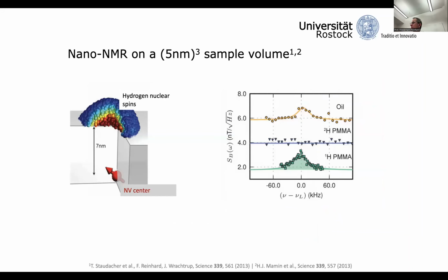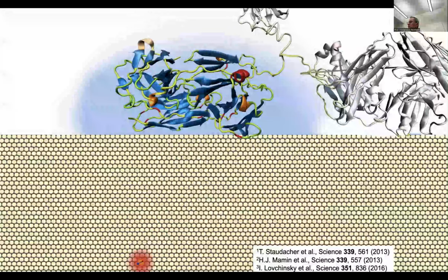And this, in fact, has been successful. A decade back, we were able to use an NV center to measure the magnetic field of proton nuclear spins in adsorbents on the diamond surface. These are the first NMR spectra that we took. And that indeed means that we can use a single atom in a diamond 5 nanometers beneath the surface to perform NMR spectroscopy on such a few nanometers small volume, which essentially is comparable to a single biomolecule in size.